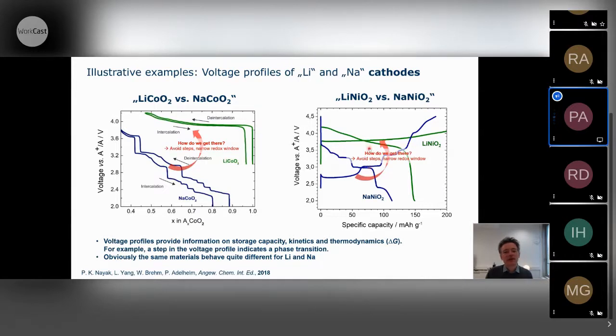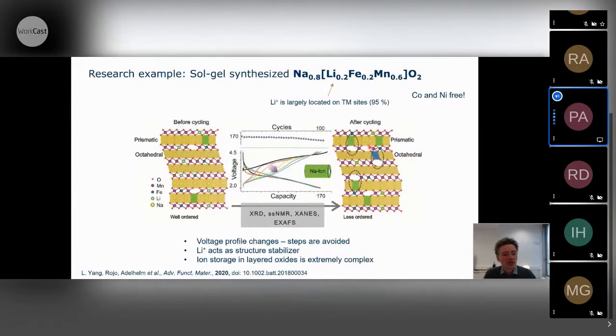And in sodium-ion chemistry, we have quite a bunch of possibilities, and this means simply you can add other elements to your layered materials to tune the voltage profile. And this is what many people do. I just show you one result from our lab. So what we look at here is a compound with a sodium content of 0.8, and then we have just iron and manganese as transition metals, and we intentionally also add some lithium. And the lithium is not sitting in the alkali layer, but really in the transition metal layer, and this way actually stabilizes the structure.